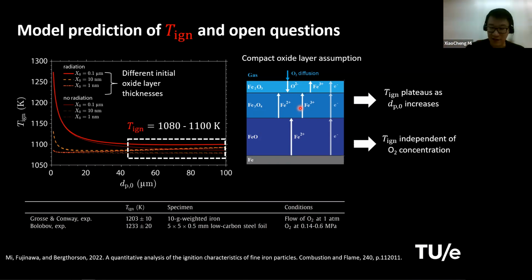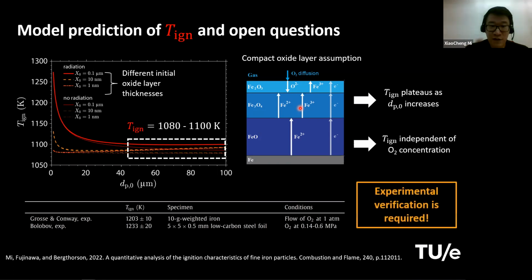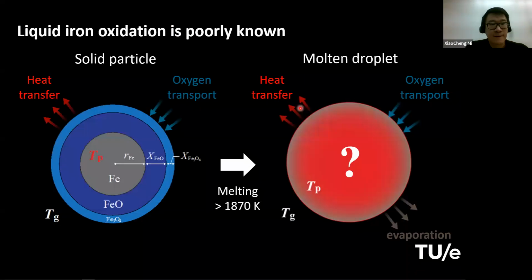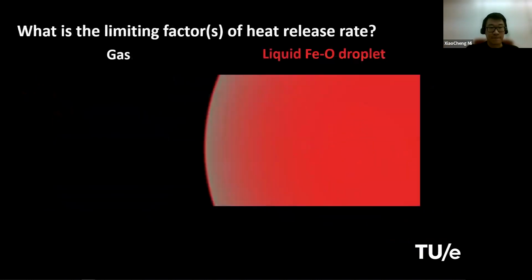But this is all based on the assumptions of this model. I'm not saying this is 100% correct, because there's no experimental measurement of particle ignition temperature yet, and experimental verification is required. And once the particle ignites, it can increase to its melting point, and then eventually the full combustion process will happen in the liquid phase, between the liquid phase particle and the gas, right?